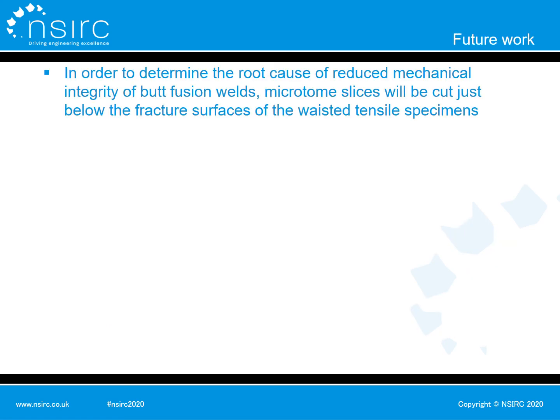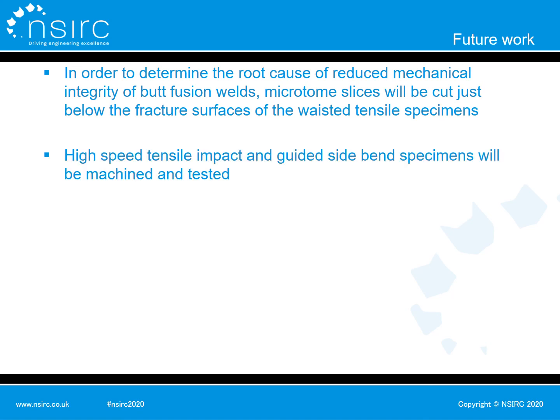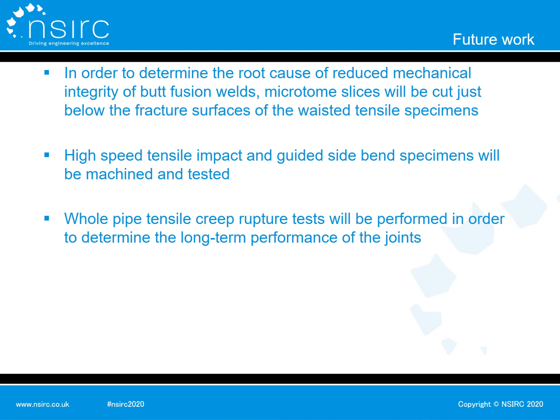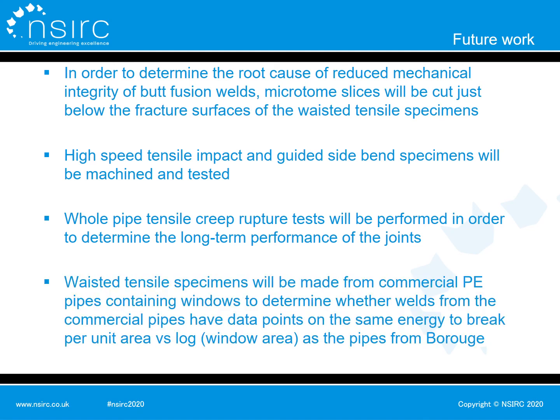In the future, in order to determine the root cause of reduced mechanical integrity of butt fusion welds, microtome slices will be cut just below the fracture surfaces of waisted tensile specimens. High-speed tensile impact and guided side bend specimens will be machined and tested. Whole pipe tensile creep rupture tests will be performed in order to determine the long-term performance of the joints. Waisted tensile specimens will be made from commercial polyethylene pipes containing windows to determine whether welds from the commercial pipes have data points on the same energy to break per unit area versus log window area as the pipes from Borouge.